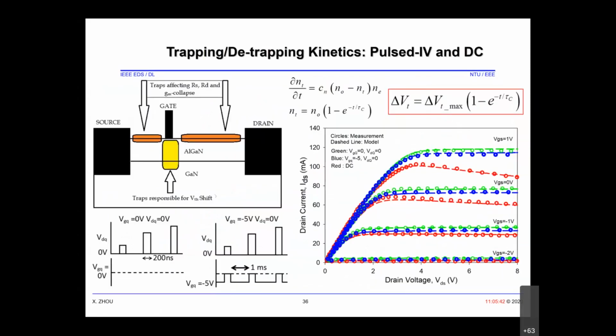Well, just a few more words about the trap modeling. As we know, for GaN devices, traps are generated in the gate region and also in the source and drain region, and it's reflected in the DC characteristics. If you do DC measurement with a pulsed DC, all these curves will depend on the pulse width, pulse duration, and bias point. Whenever you change these values, the DC curve will change. So how do we model these physically without fitting to each measurement data?